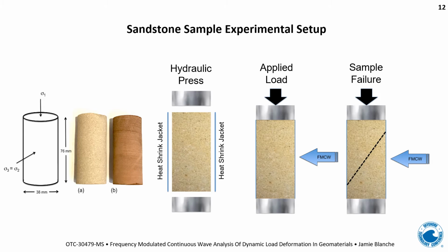These were unconfined tests. The middle image is showing you the heat shrink jacket that was applied to the sandstone samples, because when we load them, they're going to fracture, and we don't want them to lose their approximate coherence. We want to keep those samples together for later work and other characterization work as well. So we put this into a hydraulic press, we applied load, and we caused them to fail while we were reading FMCW data.